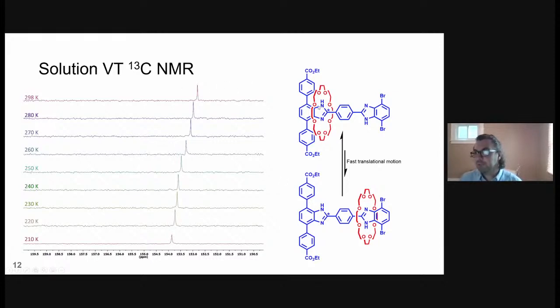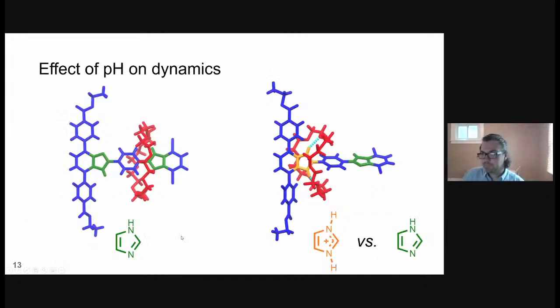Unfortunately, with this system here, we have very rapid translation. While we know that we have translation occurring, as we see a single peak corresponding to this fast motion, even at low temperature, so this is the lowest I could get the spectrometer down to, 210 Kelvin, we're still not seeing this peak broadening and separating out into two distinct peaks. So we at least have a handle on how fast this is operating, but we can't exactly quantify it.